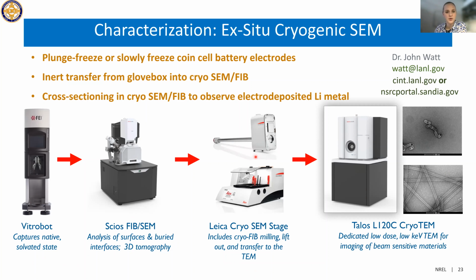And then there's tools for transferring the sample from a glove box into either a sputter deposition or into the FIB or into this platform, which then you can load and move the samples around under liquid nitrogen. It's pretty much just a liquid nitrogen bath. And then you can load the sample into a cryo holder to go into a cryo TEM, which is a cold box that sits around the sample so that you have more time to do cryo imaging, or if you need to do tomography where it's stable at that low temperature, because a lot of the cryo holders will cool and be stable for a certain amount of time, and then they'll start to heat up again, and you need to continuously cool and restabilize them. And so it's hard to get very long collection times of your data.